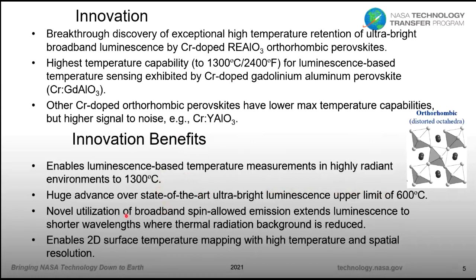Another advantage is the utilization of this broadband spin-allowed emission. This emission is in a range of shorter wavelengths than is typically used for transition metal dopants, and because you're at shorter wavelengths, you have less thermal radiation background. The high emission intensity also enables 2D surface temperature mapping, giving you both high temperature and spatial resolution.